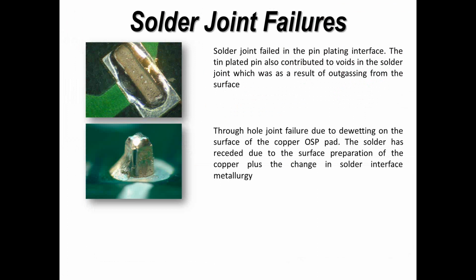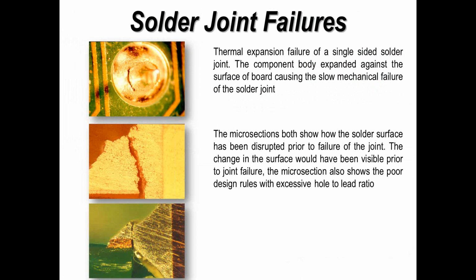Now, just a few simple examples of solder joint failures. Top example, we've got the component separating from the solder joint, and we can see outgassing. Now, if you get a lot of outgassing and a lot of voids, very fine voids at the interface, it does reduce the mechanical strength of the joint. It may not actually cause it to fail, but it can reduce the mechanical strength. In the bottom example here, we see an example of de-wetting. That was a perfect solder joint, but when it went through a second reflow operation on this through connection, all the solder wetted back to the pin and obviously decreased the amount of solder around that position.